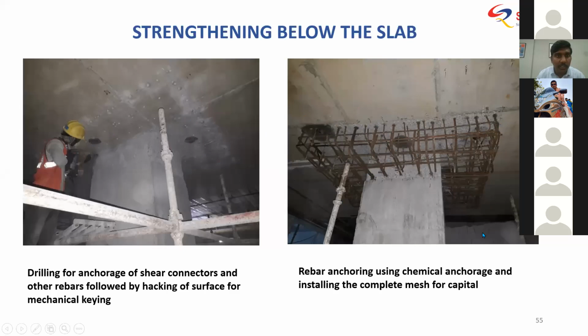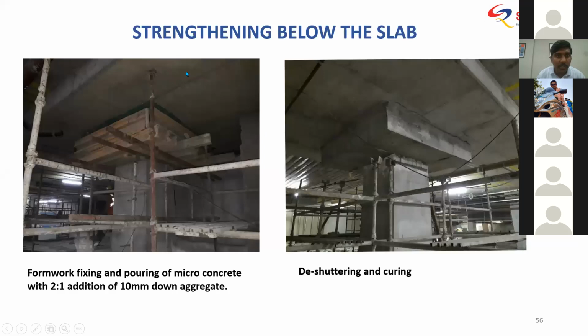It is actually a through-and-through hole. Then you put the formwork and pour concrete from the top of the slab so that it pours down through these holes, which were made earlier. After curing and shuttering and everything, your concrete capital is ready. So that was the entire strengthening process that we did for this particular project: slab strengthening from the top and bottom, and enhancing the column to slab joint by preparing a capital.